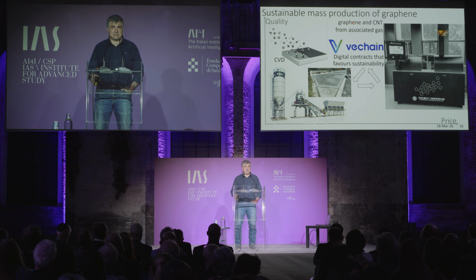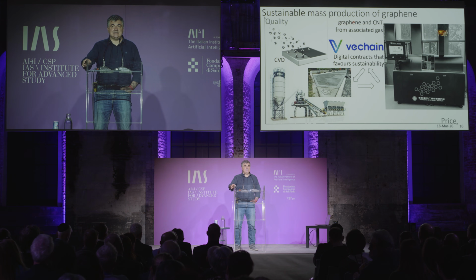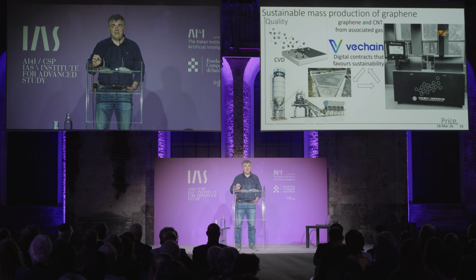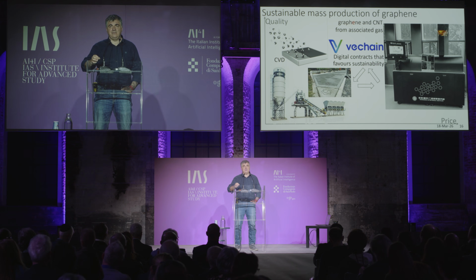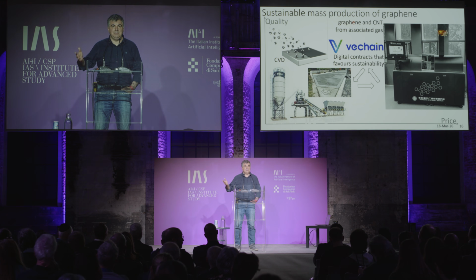graphene, and that's in the construction industry. One of the projects on this is here in Italy. It turns out that if you add a minute amount of graphene into concrete, like 0.1%, you can improve the compressive strength of concrete by 30–50%. So you add a little bit of graphene there, and you need 30% less concrete to build buildings of the same strength. And of course, the concrete industry is one of the largest CO2 emitters in the world. So what we do is take carbon from the atmosphere, put it into concrete, and reduce carbon emission even further. So it's really a fantastic example of the circular economy.